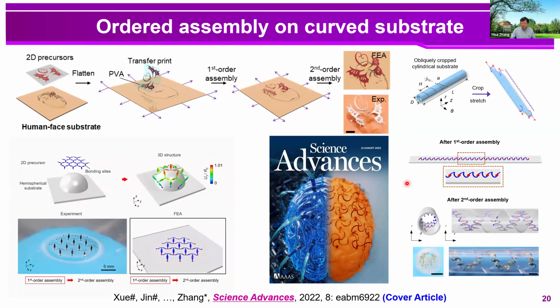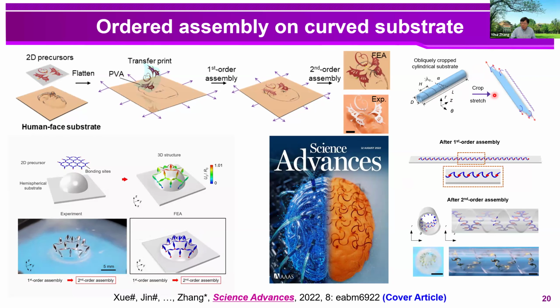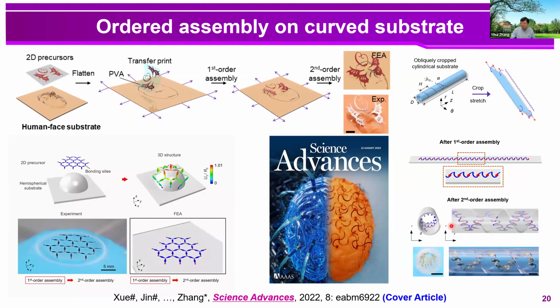In the last example, we introduced oblique cropping to a cylindric substrate such that the substrate can be flattened by bending deformations. And by doing so, we can assemble a hierarchical helical 3D structure inside the tube, which is extremely difficult to achieve by using other approaches.